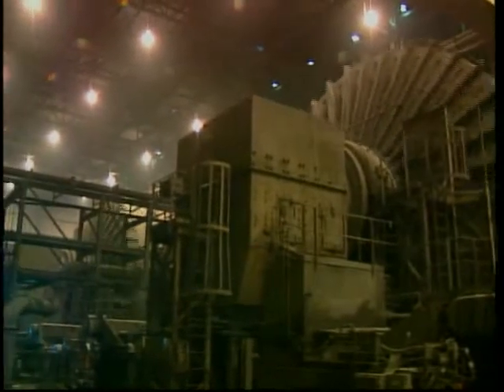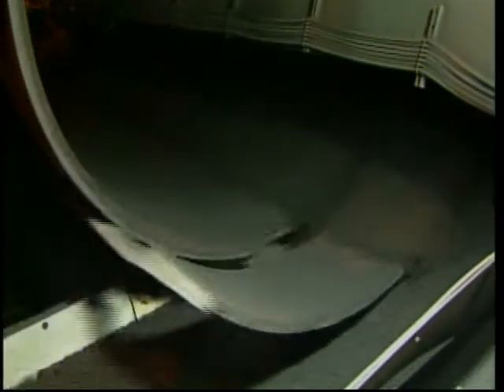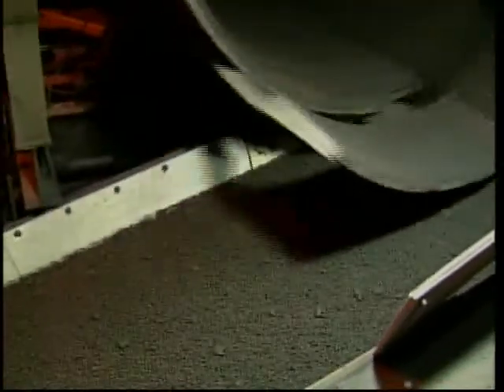The iron mineral is liberated during this process, creating a high-grade concentrate. In the pelletizing plant, the concentrated ore is rolled into balls and heat-hardened in large kilns at 2,400 degrees Fahrenheit, creating finished iron ore pellets to be turned into steel.